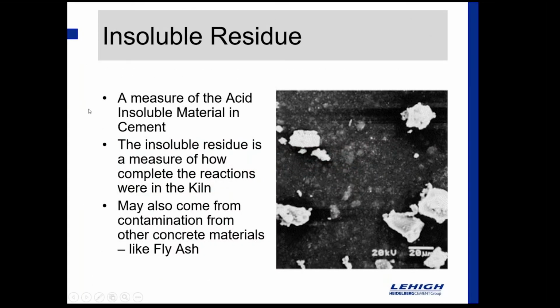Insoluble residue is a measure of the acid insoluble material in cement. And the insoluble residue is a measure of how complete the reactions were in the kiln. Could also come from contamination. Like again, if that tanker carried something like fly ash before it had cement in there, that fly ash could raise the insoluble residue count in your cement sample and cause you an issue, perhaps with a state DOT or something like that.